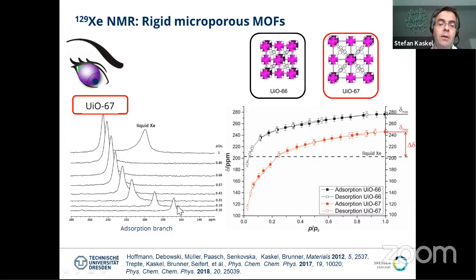And then we see that basically with increased filling, the chemical shift of the xenon shifts to higher values. And for the UiO-67, this is this curve here. And we can call this maybe a type 1 or type 1b isotherm that we see here for this type of pore system. What is quite funny, this looks like a normal isotherm where you put the uptake here, but this is not the case. This is not the uptake, it's just the chemical shift. So the chemical shift resembles the adsorption behavior very well.